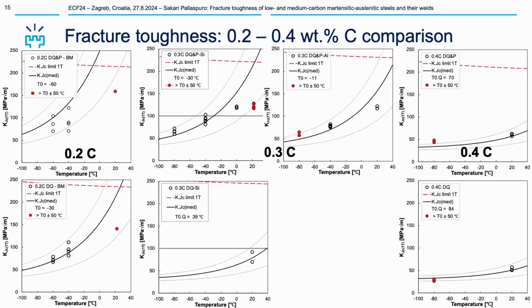To start with this carbon range for these fracture toughness properties, the most curious thing here is that if you do ambient temperature testing, we start to drop out of this temperature dependence. Basically, the austenite there may not improve the properties to as high an extent as hoped, with the high local stress concentrations. But what we can get is very good low temperature toughness properties.